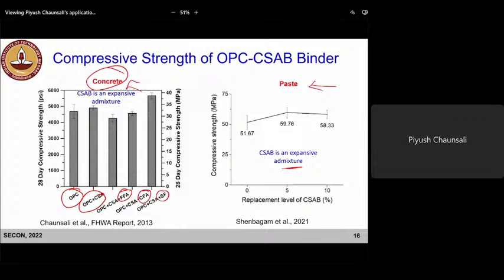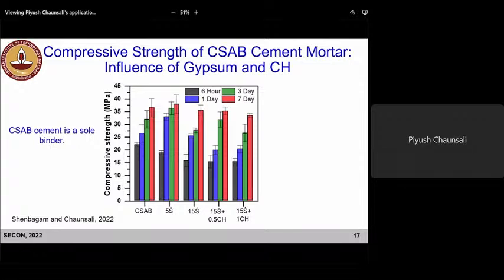So this is basically an OPC CSA blend, where 85 to 90% is OPC and 10 to 15% is CSAB. Again, this is for getting the expansion so that we can develop a shrinkage compensating property. But we'll see later, in this case, CSAB cement is a sole binder. So you can have a CSAB cement which will not expand. Basically, it's a non-expansive CSAB cement, right? And we know that this will depend on the M value. What is the M value? How much gypsum you have? What is the gypsum to yeelimite ratio? So we have both types, expansive and non-expansive.